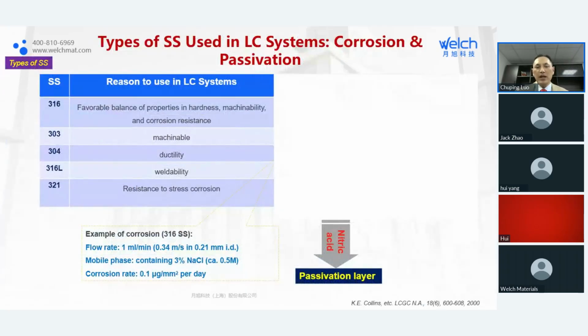People say, oh, there are many types of stainless steel used in the system. Are they doing the same thing? Yes, exactly. You see that corrosion happens continuously in most environments, including low pH, of course, and even hydrochloric acid. Everyone can agree that hydrochloric acid is not good. But what about DMSO? What about phenol? What about citrate, fluoride, EDTA? All these things can impact the surface.